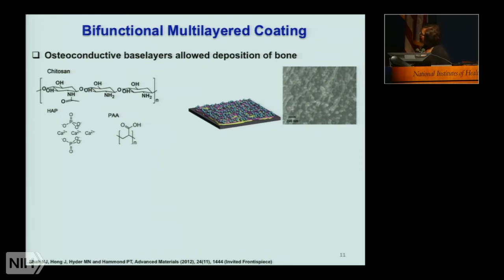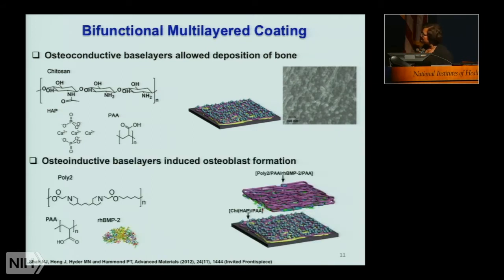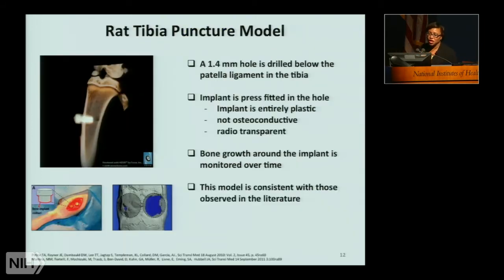Now we have this base layer that will allow deposition of bone. And on top of that, we're going to place layers of BMP2, which can release over an extended period of time. So this is our early experiment. We haven't introduced the anti-infective yet. We'll get to that. But we first had to ask the question of whether or not we can generate a strong bone material interface. So here we used a rat tibia puncture model, which is demonstrated here.